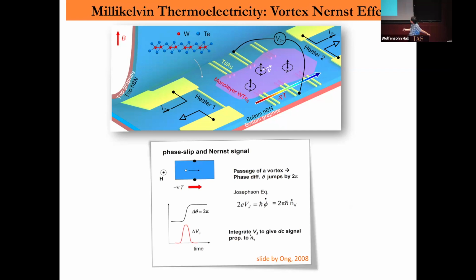This was first applied by N.P. Ong to investigate cuprates, and there was a lot of exciting developments in that area. So the key idea here is, assume you have a superconductor, and then you apply a temperature gradient. Let's say you have some magnetic field, so you have a vortex. And then if you have a temperature gradient, the superconductor is a condensate, which is very quiet.